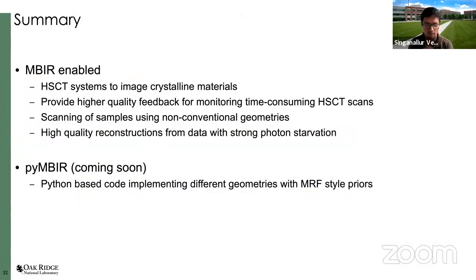So to summarize this section, we talked about model-based methods for hyperspectral CT systems, where by designing new forward model terms, we are able to allow for the imaging of crystalline materials. By acquiring the data differently, we are able to provide high quality feedback to users in these shared facilities, right? There are many people wanting to use it and it can be very useful. We showed how model-based techniques can help in scanning samples using non-conventional geometries, which again can be useful if you have parts which have odd shapes and you want to scan them. Having the flexibility to orient them differently and reconstruct can give you all the usual benefits of the model-based approaches along with this additional one. And we also showed how we can get high quality reconstruction for cone beam data with strong photon starvation using model-based techniques. So these approaches are very powerful.